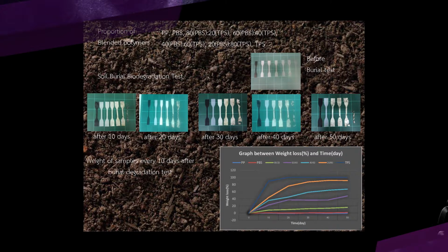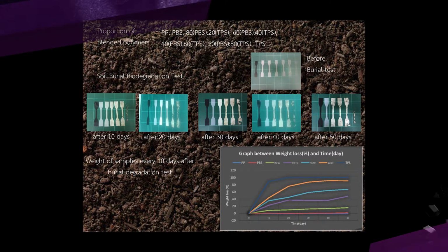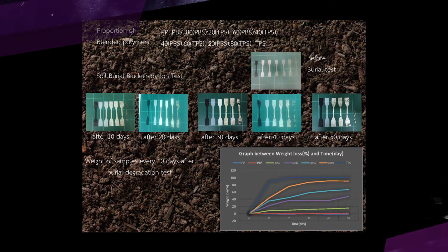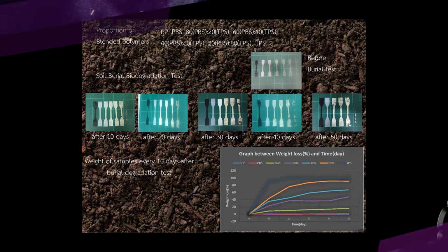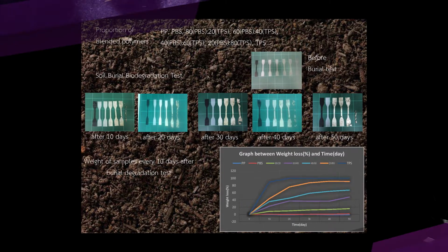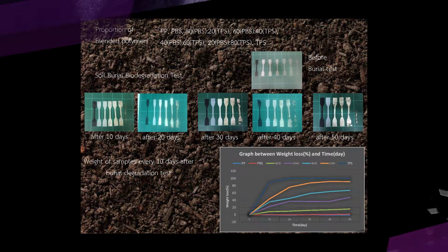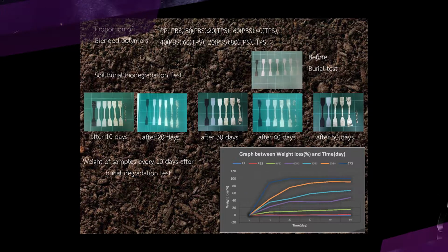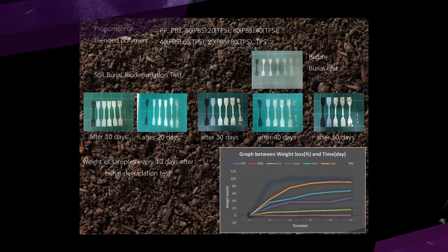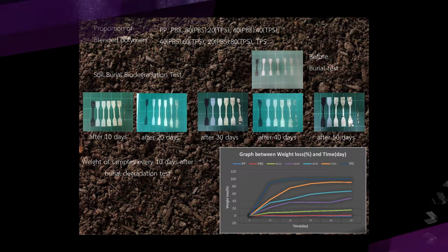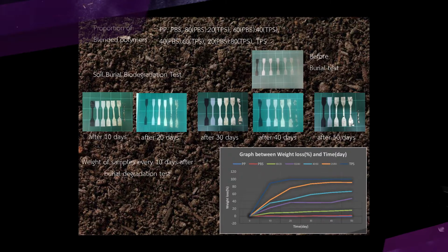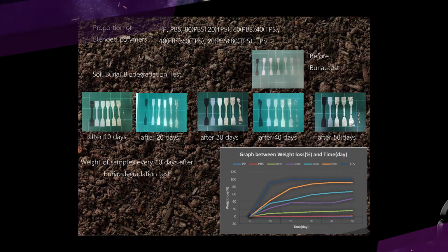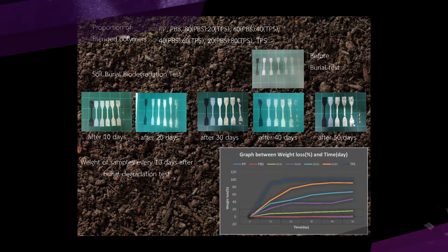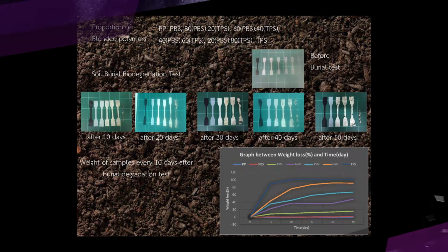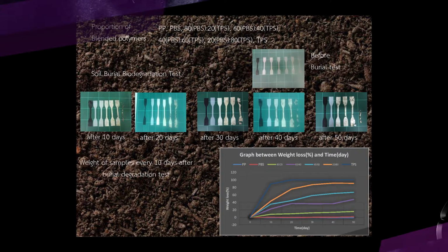Degradation of the blended polymer is investigated by using an outdoor burial test. These specimens are removed and weighed every 10 days until 50 days. This graph shows the degradation of the blended polymer. You will see that the more thermoplastic starch proportion, the more quickly it degrades compared to the others.